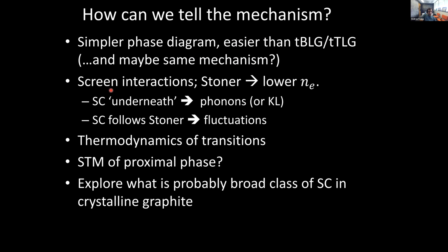One idea that we are pursuing is to screen the interaction. So you can use a van der Waals heterostructure to, for example, put a metallic plane, probably made of graphite, very close to the 2D layer, closer than the inter-electron spacing. This should lower the Coulomb repulsion by quite a bit, because if you have electrons 10 nanometers apart, but you put a metallic plane 3 nanometers away on both sides, you're essentially going to exponentially screen that repulsion. And so presumably you will suppress these types of Stoner transitions down to lower density. You'll access higher density of states without symmetry breaking.